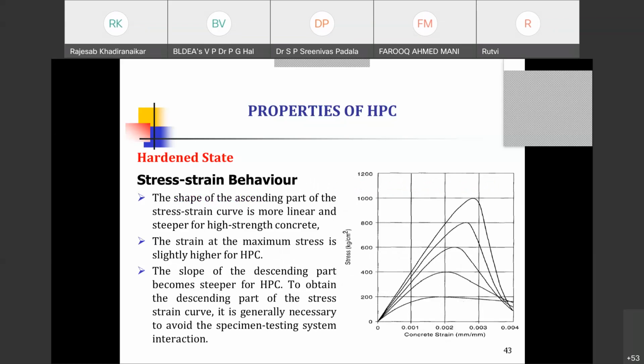So another important property of your HPC is the stress strain behavior. Stress strain curves occur for different grades of concrete. This is conventional concrete, and then strength increases, and increases. You'll find that there is a distinct difference in the shape of the stress strain curves for different grades of concrete. There's a change in the ascending part also, and the ascending part of each of these curves is not similar to the others, nor are the peak behavior and the post-peak behavior. They are distinctly different when the strength changes.